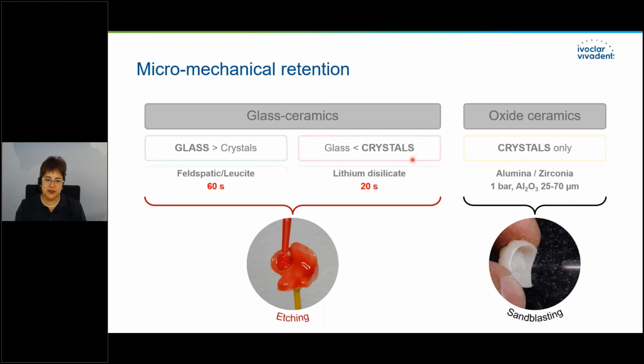have higher crystal phase. Since feldspathic and leucite reinforced glass ceramic has a bigger glass phase, we need to etch longer than lithium disilicate glass ceramics with lower glass phase. The longer we etch, the more we expose the crystals. When the crystals are exposed, the resin cements are able to infiltrate the gaps and to create any kind of retention. Important is not to over-etch, because otherwise you will overexpose the crystal phase and you will change the physical properties. And this is crucial, especially for veneers, because the ceramic can turn opaque.